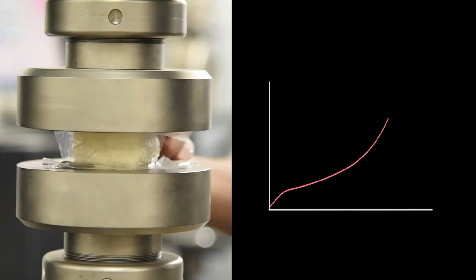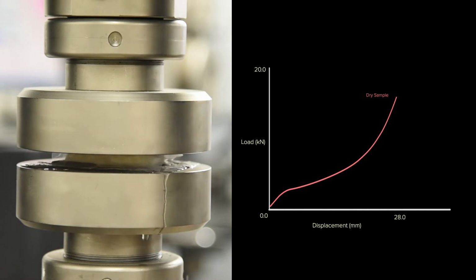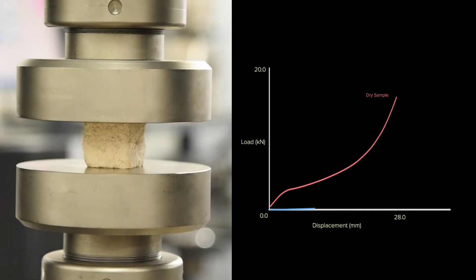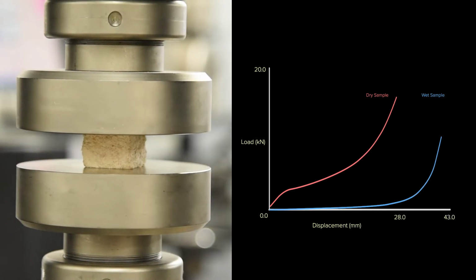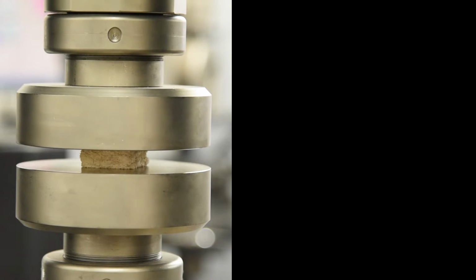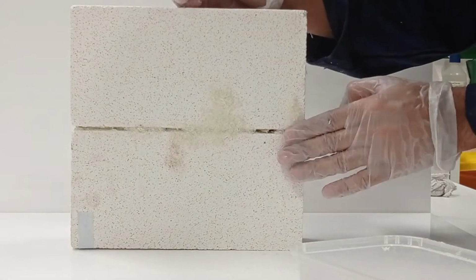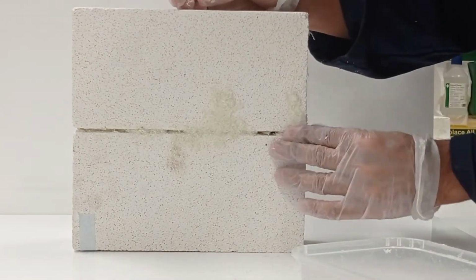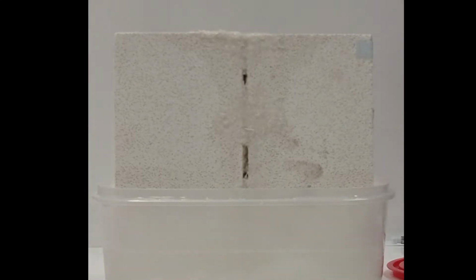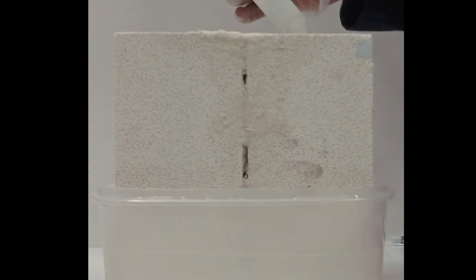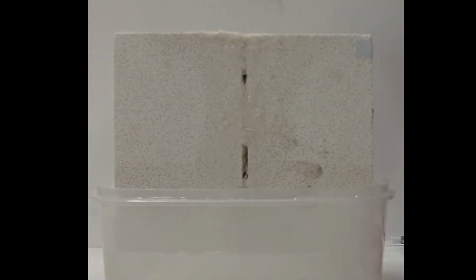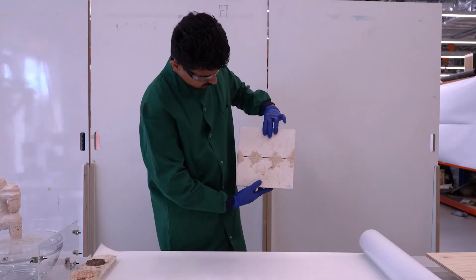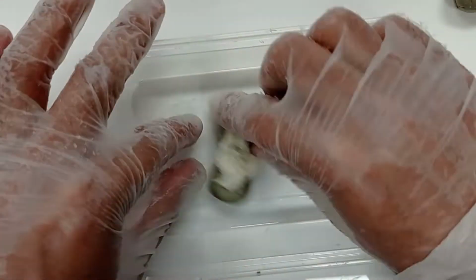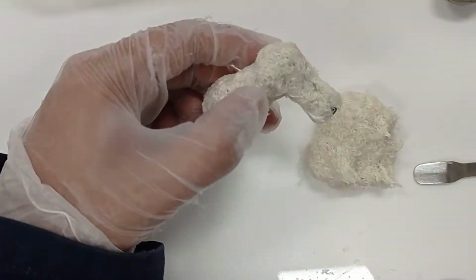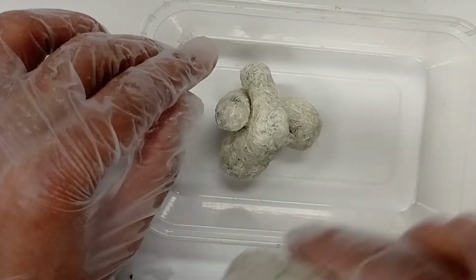The compressive strength of a dehydrated hydrogel composite could nearly match that of a regular sun-dried brick. The hydrogel composite substrate is used as a mortar to bind bricks together. The cross-linking of hydrogel with plant fiber provides high mechanical strength. And yes, you can pick it up as well. The substrate is also used as a surface coating.